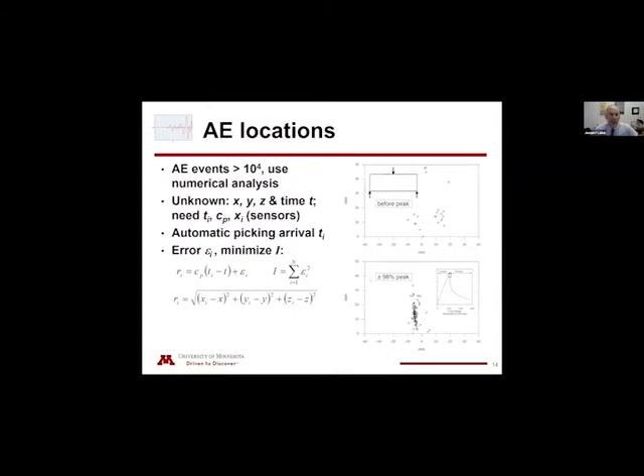Okay, as I said, we record thousands of events, and the solution then needs to be developed where we have a numerical algorithm. We have 4 unknowns, and we can set up an optimization problem where we minimize an error to find these 4 unknowns. The things that we do know, the arrival times, we take the P wave as a known quantity. It can be treated as an unknown and found within the minimization procedure. I mentioned the automatic picking of the first arrivals. And again, this is set up to be solved in a least squares type of algorithm.